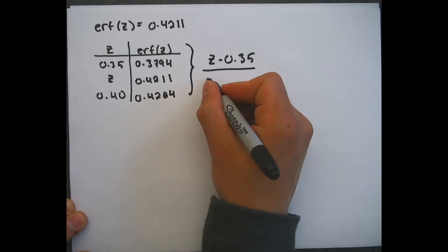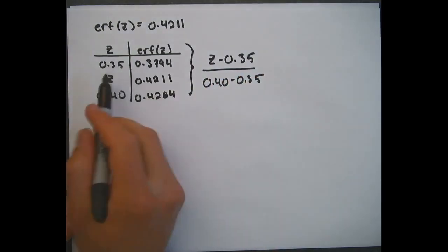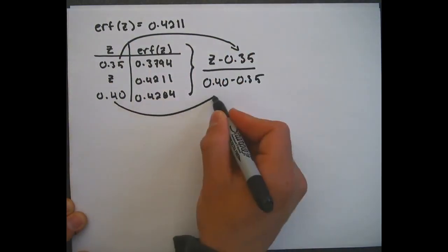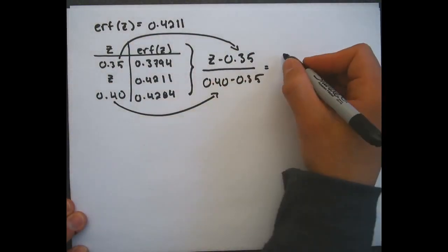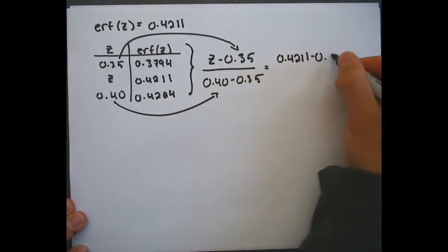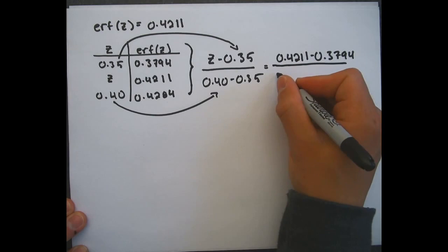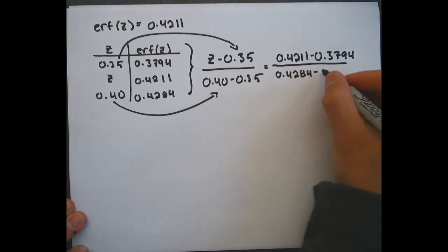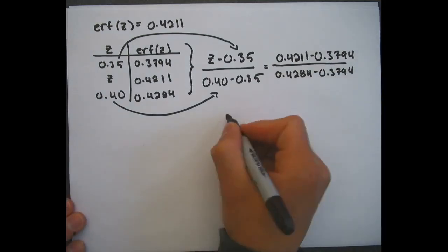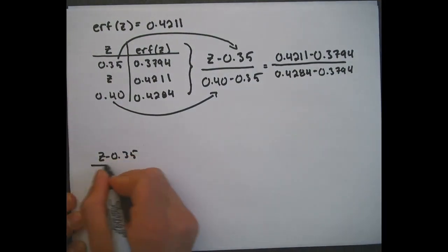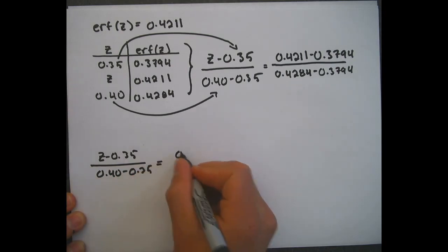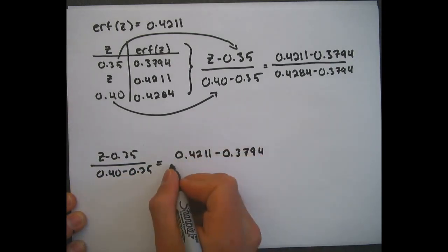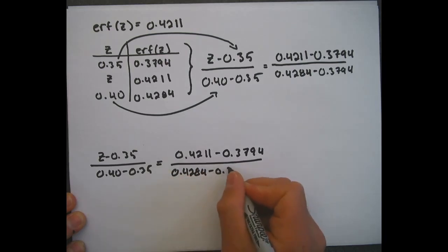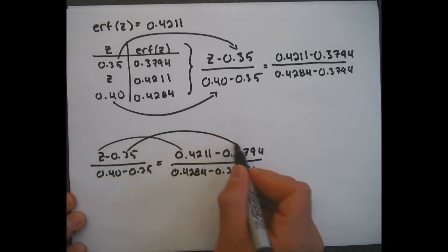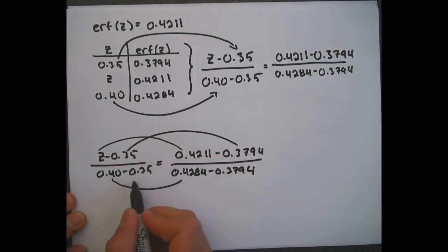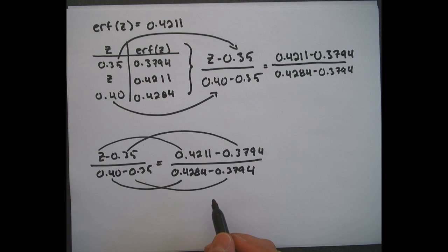To write out this formula, we do z minus the lower bound z, over the higher bound z minus the lower bound z. You can see how that relates. We set that equal to the error function of z minus the lower value of the error function, over the higher value of the error function minus the lower value of the error function. You can see how these all relate to one another. This is how the equation looks without any of the arrows. Now you can see it's the upper bound minus the lower bound in the denominator, and the error function value minus the lower bound in the numerator.